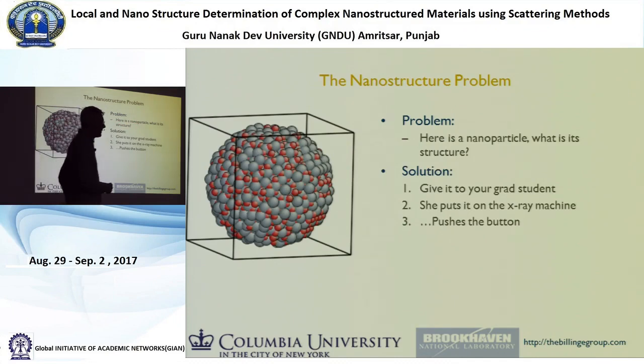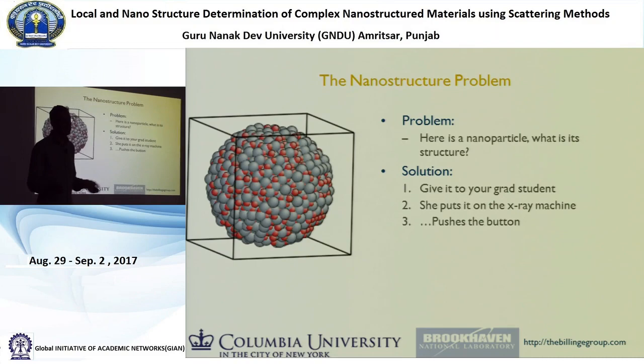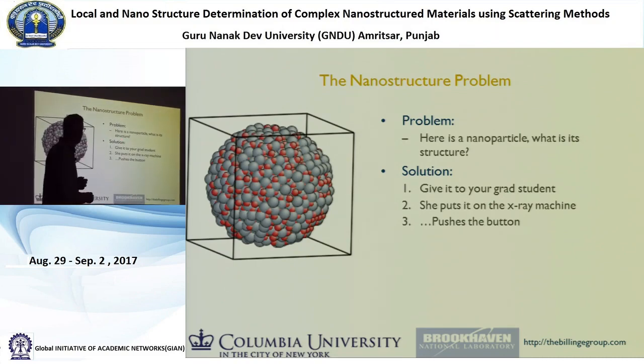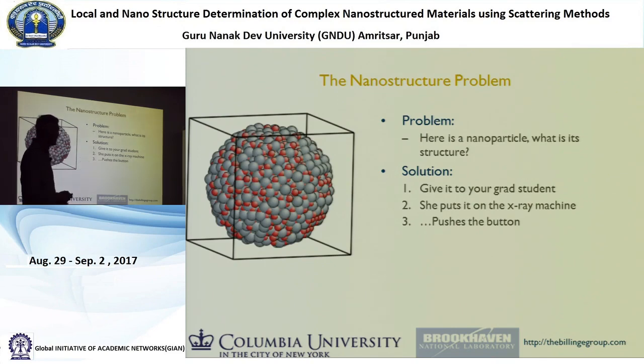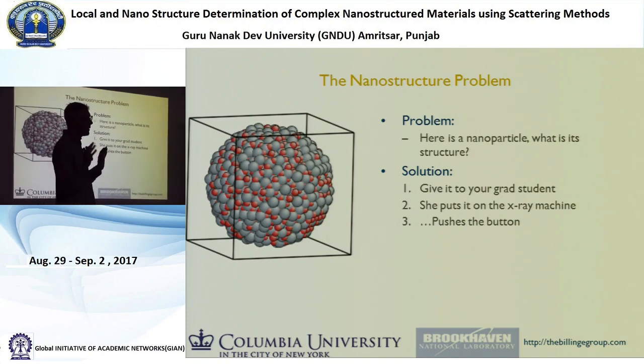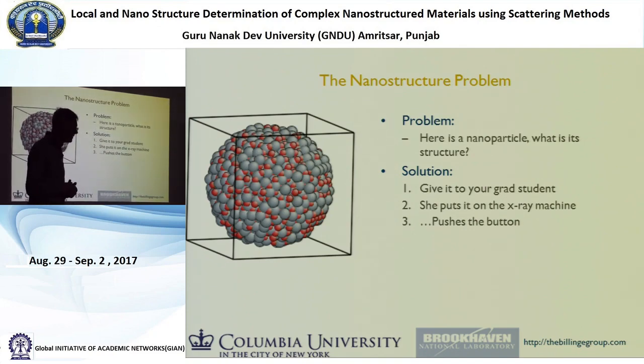So in my group, we're not very smart, so we always try the solution that's already been tried. So we give the nanoparticle to the student, and then she puts it on the X-ray machine. That's if she doesn't drop it. Like, it's not easy to mount a nanoparticle on an X-ray machine, right? But then she manages to get it on the X-ray machine, and she pushes the button, and absolutely nothing comes out of the X-ray machine. And the reason is that there's not enough atoms in this object to scatter enough X-rays that you can measure them. So that's problem number one, is just getting a signal from the nanoparticle.